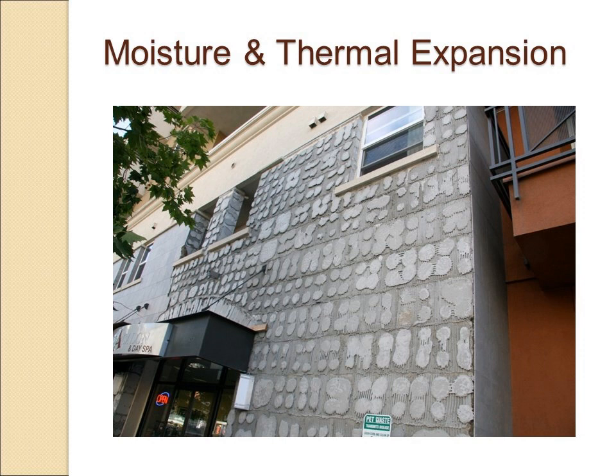And with every failure, every one of us knows it's not just one thing that causes a failure. So we know that this was done incorrectly, but the issue is according to the building movement and thermal expansion, due to moisture getting into the system, getting into the materials, that's what causes the failure. It's a combination of the two.